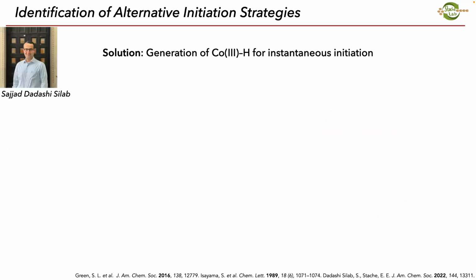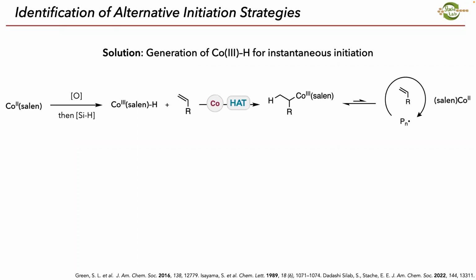And so my postdoc, Sajad, developed an instantaneous initiation method where we don't have to wait for those radicals to be generated over time, and we don't have to worry about those side reactions. And so what he did is he took cobalt-2, he oxidized it, and then treated with a silane to generate a cobalt-3 hydride, which can rapidly add across the alkene, and then we generate the same species that we saw before, except we do it instantaneously.